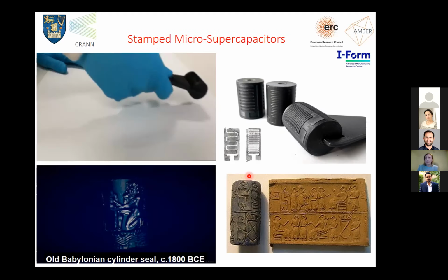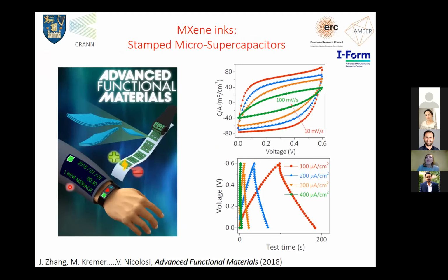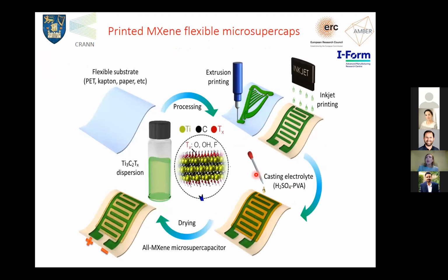And we were indeed amazed by the fact that these devices, printed in a blink of a second, really worked extremely well. It started showing some resistive behavior at 100 millivolts per second, but at low rate they were working amazingly well. And this is extraordinary, because all you have there is one roll, one thin layer of material stamped on paper. That really gave us confidence to pursue things that were more sophisticated.